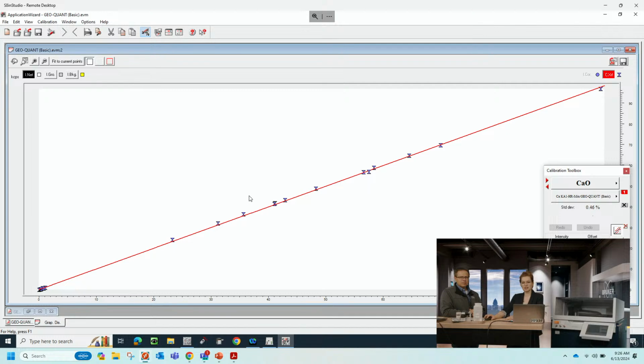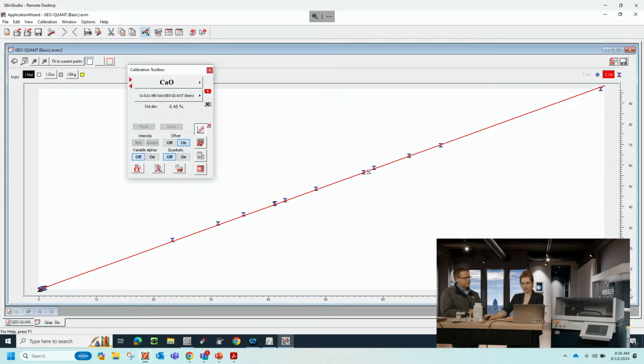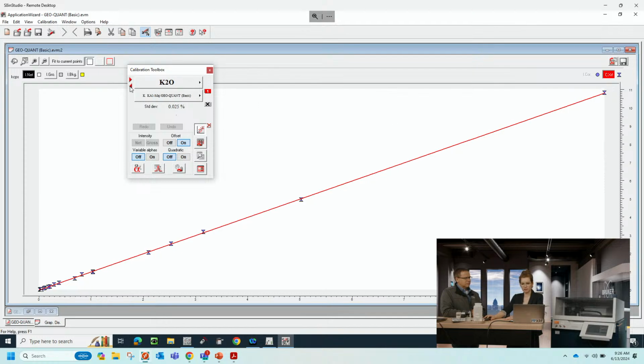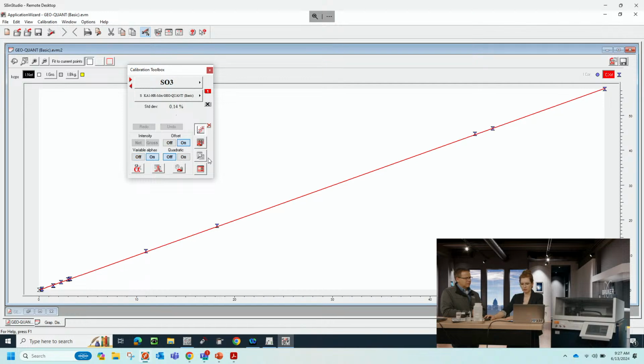Right? And this is an example of a fused bead calibration. So we can see, I don't know if you can see that, but it goes from 0 to 90% for several elements, right? We have 0 to 15% potassium, 0 to over 50% sulfate, phosphorus goes up to 7, silicon oxide 0 to 100%, aluminum 0 to 80%. That's why you use fused beads, right? Because you can mix several different matrices because it's all a glass.